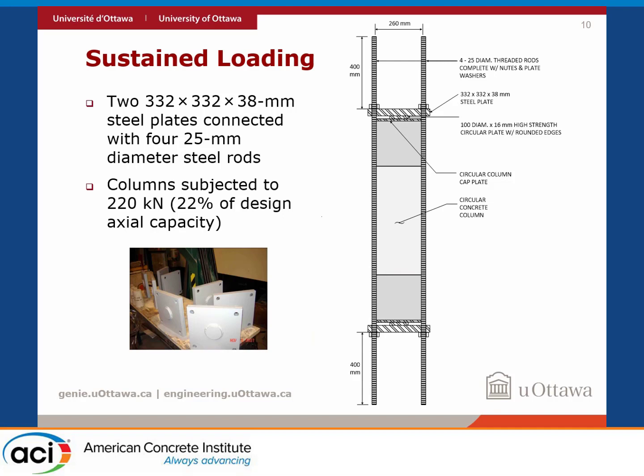This is the setup that we used for the sustained loading. We had 2 steel plates at the top and at the bottom that were connected by 25 millimeter steel rods that were subjected to tension and were applying compression to the specimens. The column was placed between those plates, and there was a 16 millimeter thick round plate between the plates and the steel caps of the columns that was welded to the outer steel plates, but was just touching, without a bond connection, the steel caps of the columns to allow for pin connections.